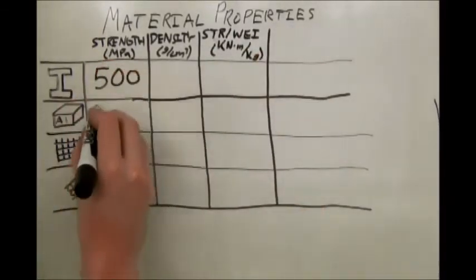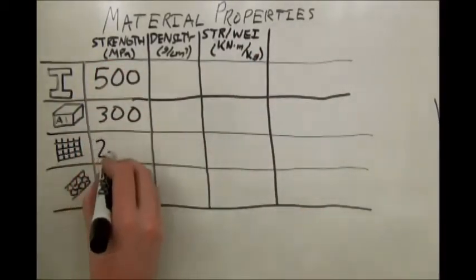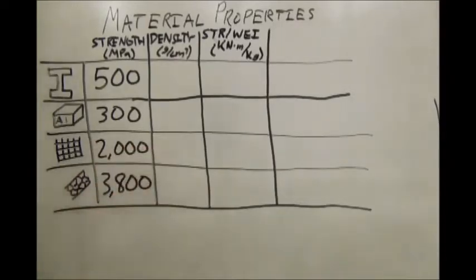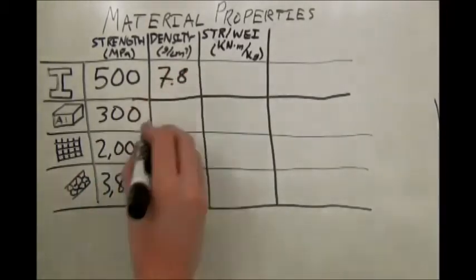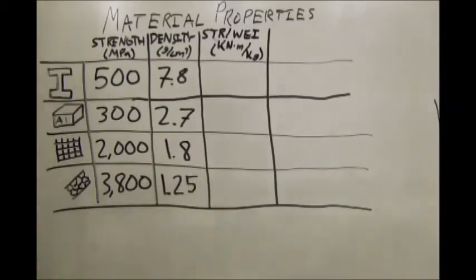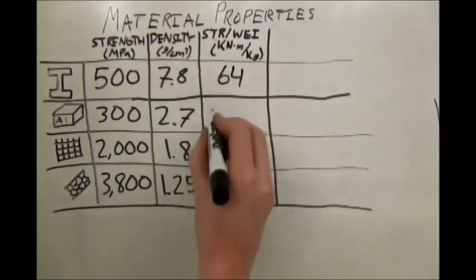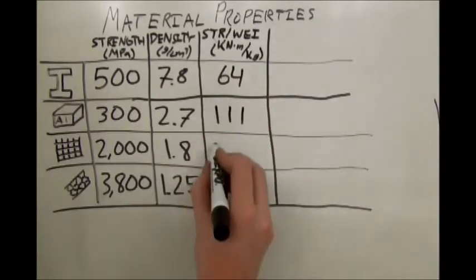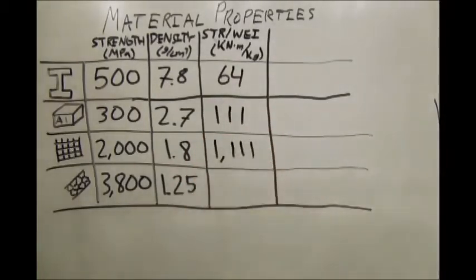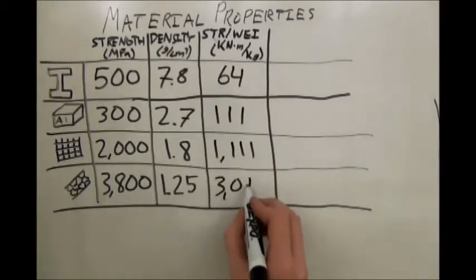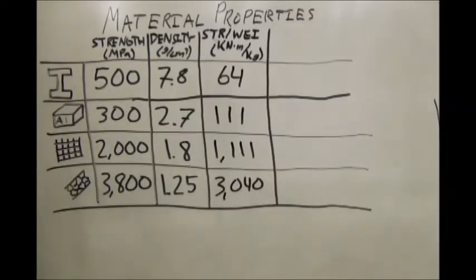The strength of steel and aluminum are similar when compared to the values of the composite materials, which are 4 to 10 times larger. The story remains the same when it comes to the density of these materials, which, despite their higher strength, have a much lower weight per cubic centimeter. The high strength and low densities seen in the engineered composites mean that the strength-to-weight ratios of these materials are an order of magnitude larger than those of the natural steel and aluminum.